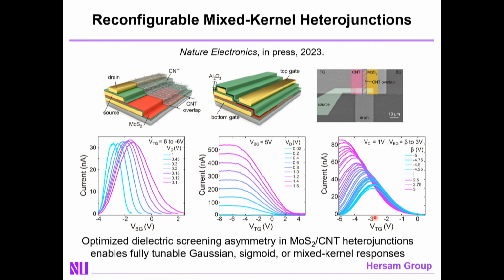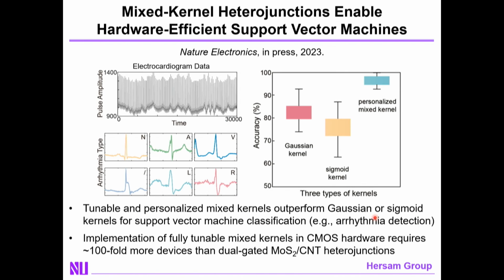This is also of high interest for machine learning. In machine learning, one of the first classification algorithms you learn in undergraduate machine learning is the so-called support vector machine. And when you look at support vector machines, the gold standard is not to do a single Gaussian or sigmoidal kernel, but rather to mix the two together. We can now do that mixed Gaussian sigmoidal kernel in hardware using a single device. If you attempt to do the same machine learning hardware equivalent in CMOS, it requires 100-fold more devices, which is why it's typically not done. It's just too cumbersome. But with a single device, it can be done in a highly efficient manner.